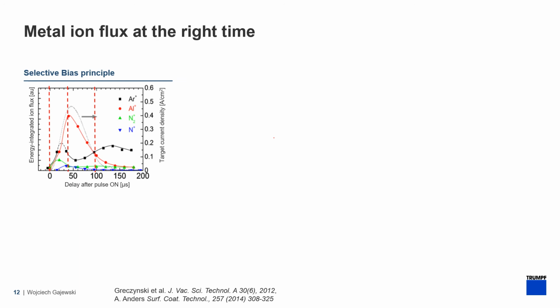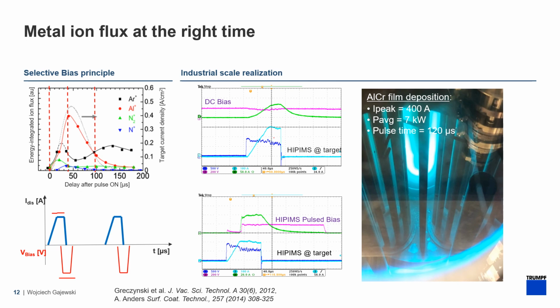In previous slides, we have already discussed how important the cooperation is between the HIPIMS and the HIPIMS bias power supplies. In 2012, Greczynski published a very important paper in which he and his co-authors showed that if we use a pulse bias and shift it with respect to the HIPIMS signal, we are able to tune the properties of the coating. This solution has already been tested in industrial size systems, and indeed the shifting of the HIPIMS pulse bias with respect to the HIPIMS does influence the quality of the coating.